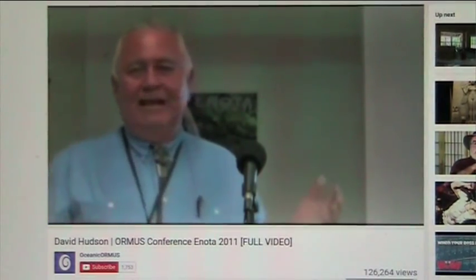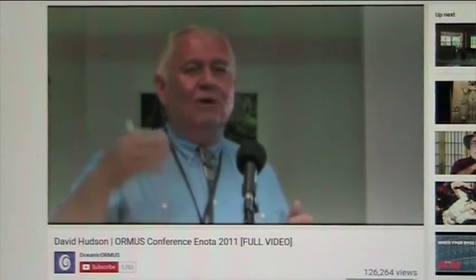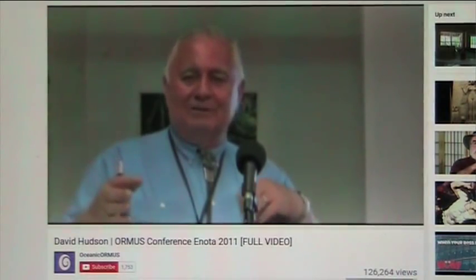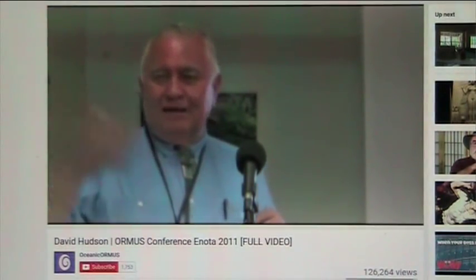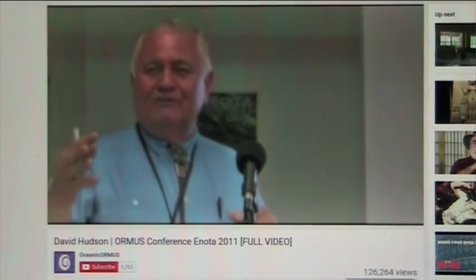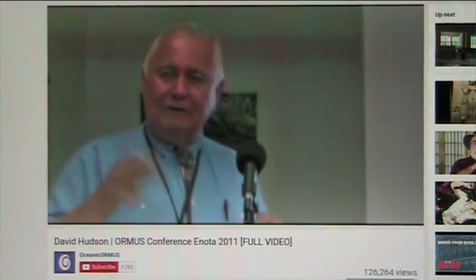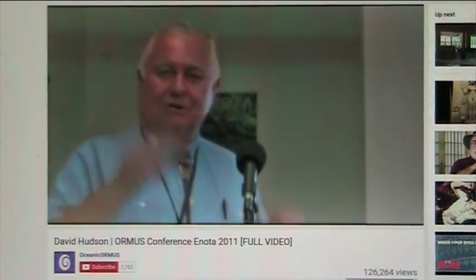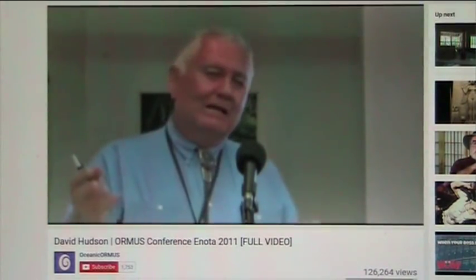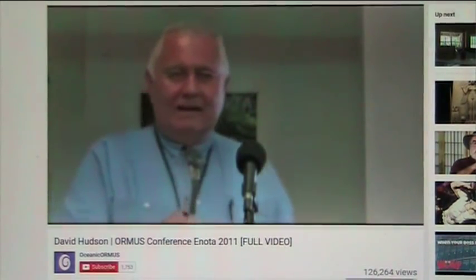Well, according to the Soviet Academy of Sciences, you heat it under oxygen up to 800 degrees, and it forms an oxide. And then you put an inert gas in there, usually argon, to get all the oxygen out, and then you put hydrogen in. And then you hydroreduce for 15 to 20 minutes, and then you cool it down under hydrogen if you want a hydrogen compound. But if you want all the hydrogen out, you cool it under an inert gas like argon or helium. You cool down to ambient temperature, then you reach in and take the cork out, pull a sample out, and you put it on a scale and weigh it.